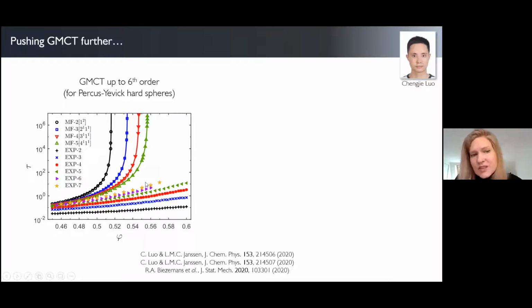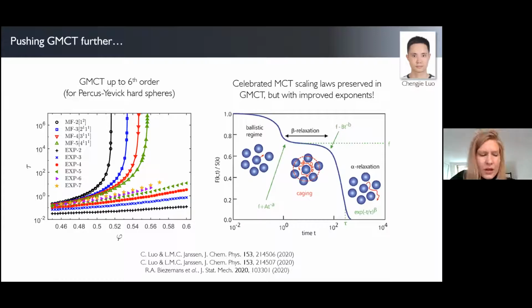And so this is up to 6th order, and it would be interesting to see where these 2 families of closures would meet if we would be able to push this to infinite order. And secondly, I also briefly mentioned that standard mode coupling theory predicts these universal scaling laws for the dynamics. And so Chen-Jie also analytically derived that all these scaling laws are fully preserved in generalized mode coupling theory at arbitrary order. So that's great, but the exponents in these scaling laws, so there's certain power law behaviors here, those exponents can change quantitatively and even improve as you go to higher order in this framework.